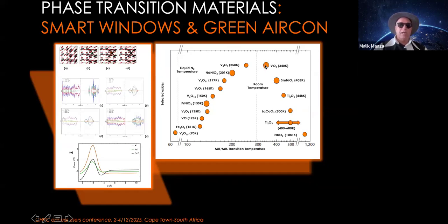VO2 is a semiconductor at low temperature, and it's metallic above a certain temperature, which we call the critical temperature. But the critical temperatures of VO2 variants are not all suitable except this one. Why? Because its temperature is close to room temperature, but it's still high: it's 68 degrees Celsius. What does it mean when it is metallic? VO2, vanadium dioxide, is metallic. That means it stops the heat. It stops the infrared. Any metallic coating stops the infrared. Any semiconductor material will allow the infrared to come in. It's transparent.